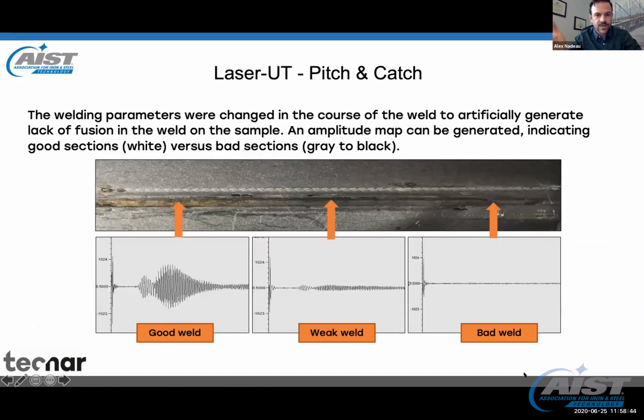This is an example of a scan in the pitch catch mode on an overlap seam weld. And you can basically see the sound picked up on the other side for a good weld. And now there's no advanced frequency analysis. That's just a mashup of lamb waves and longitudinal and shear waves, but basically by the amplitude of that, you can see that that's a good weld. In the center, that's a weak weld with much less sound. And basically on the right, it's just a complete lack of fusion. So it's pretty bad. There's no sound going through at all.